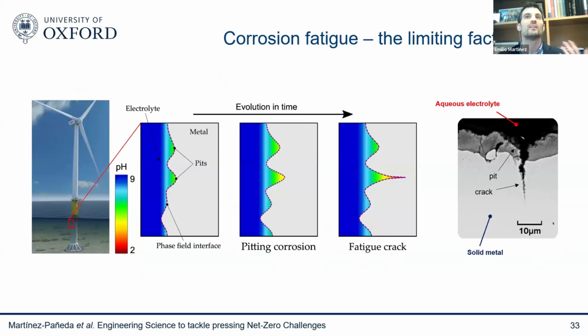So what we're trying to do is, again, bring this idea that maybe we can develop models that are mechanistic, that explicitly resolve the underlying physical processes, and therefore allows us to predict what's going to happen. And the reason why these wind turbines only last 25 years is corrosion fatigue. So is the fact that you have a monopile, a metallic monopile, a carbon steel, a structural steel in a very aggressive environment, a seawater environment. That generates pits. Those pits are going to grow, driven by local chemistry and mechanics. And eventually you get the pit to crack transition and the propagation of a crack.